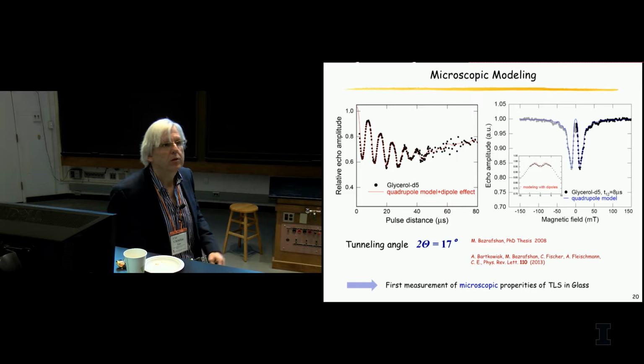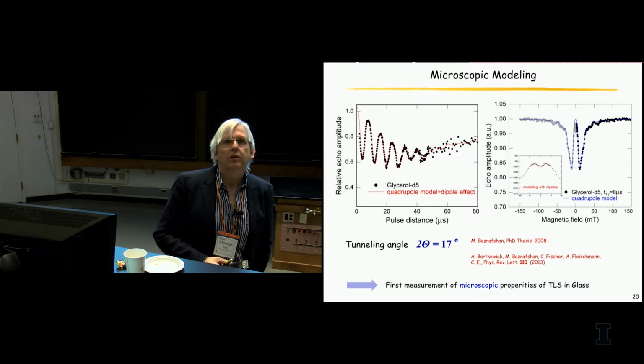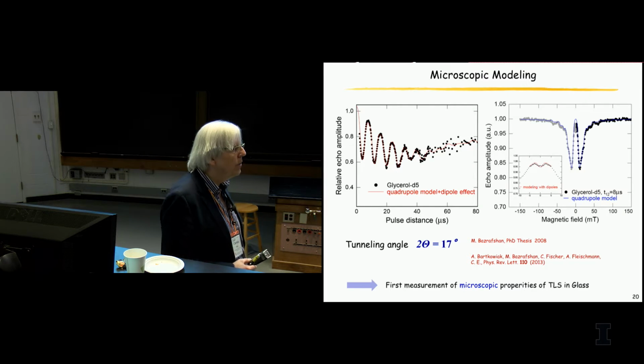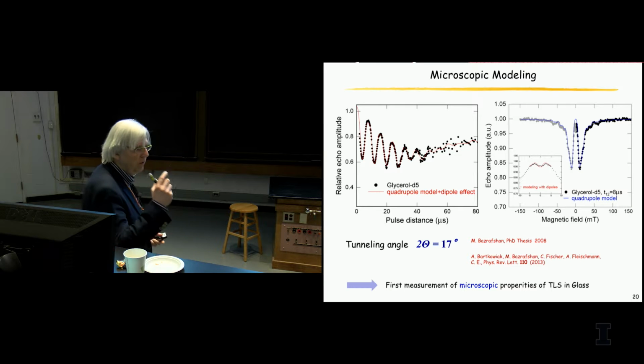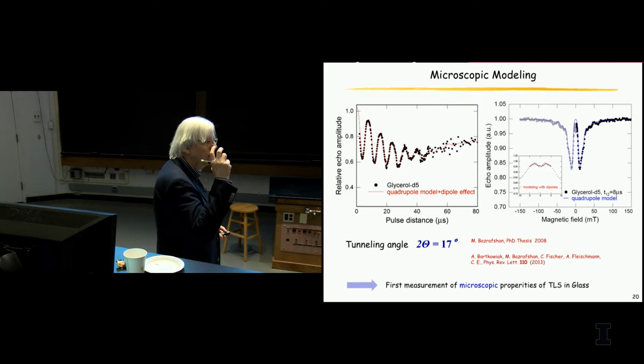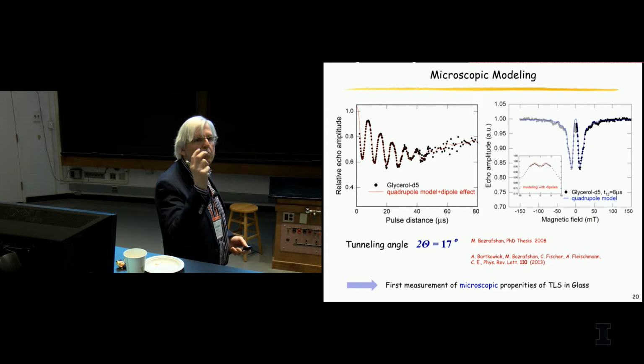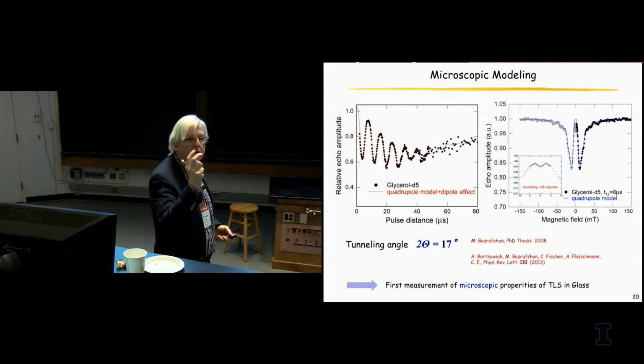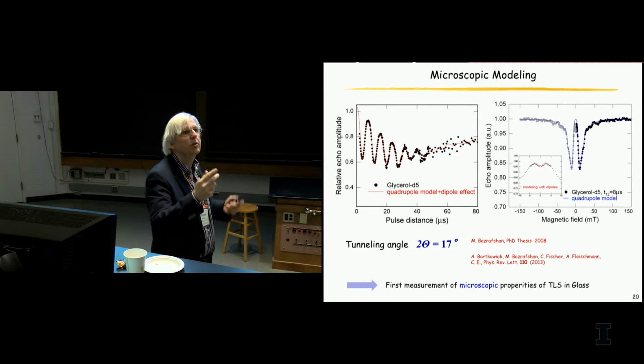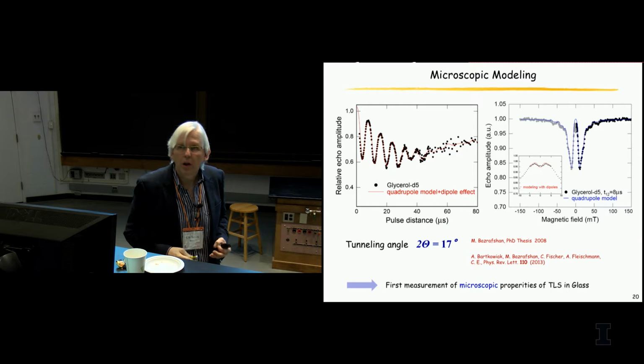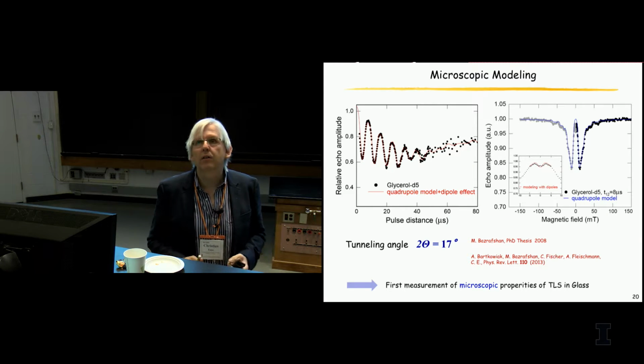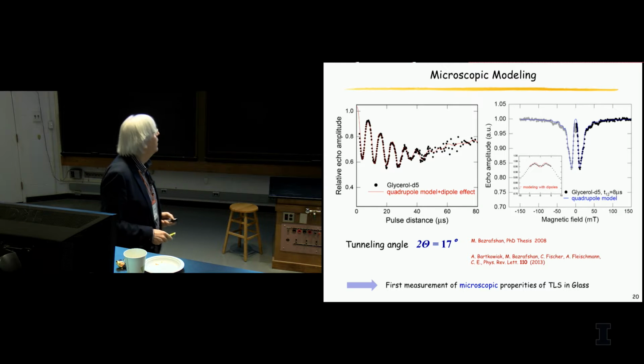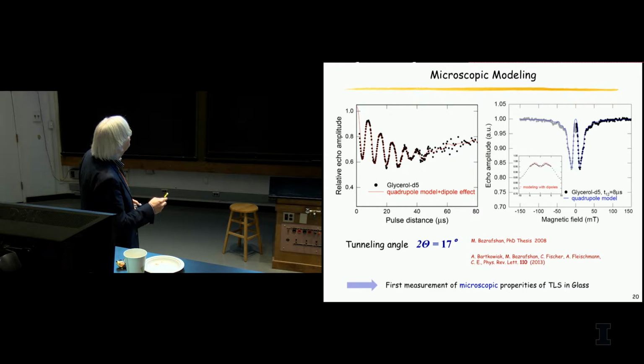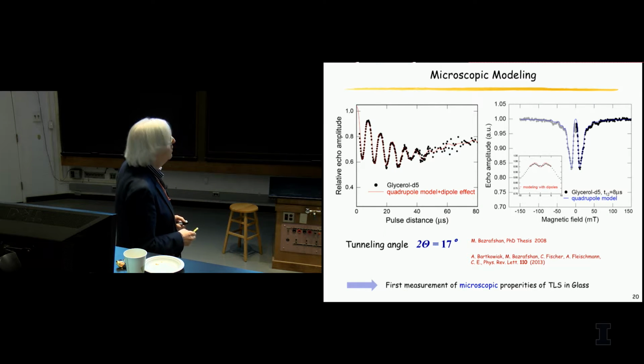You can model then, you can ab initio calculate what the echo amplitude is in magnetic fields if you assume that you have a rigid glycerol molecule just rotating a little bit in this matrix. This was an assumption we made, and we asked whether one could, in fact, microscopically describe that. And what you can see here, this is the blue line, and the points underneath are the experimental data, and the description is really, really nice.